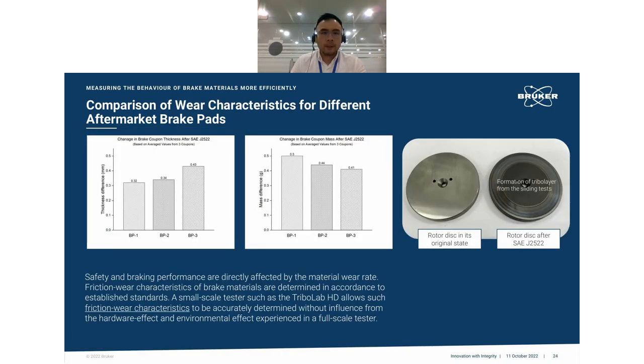Wear has been a very important characteristic that has been evaluated. Same goes for us. In this test, we monitored the wear of the three different brake pads after the entire AK master test. For developers and manufacturers, this is an important aspect because the material wear rate would signal the safety and the braking performance of the formulation.